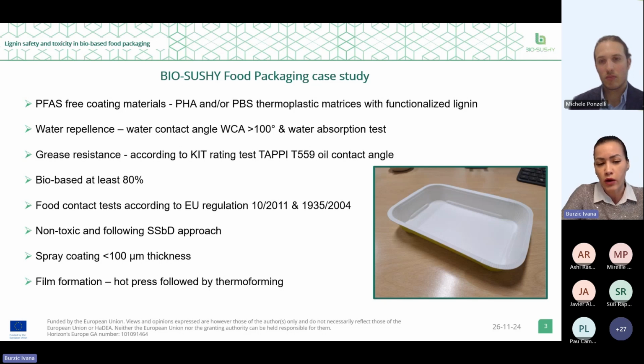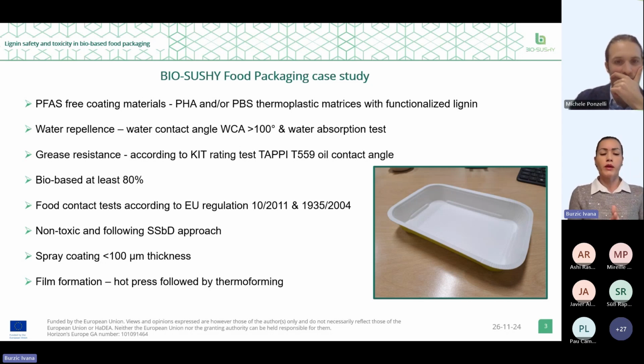As mentioned, spray coating is the technology to apply the materials on paper. The target is 100 micrometer thickness. Here we observe film formation, an ultra thin coating layer on paper, which is followed by hot pressing and thermoforming to obtain the food tray.